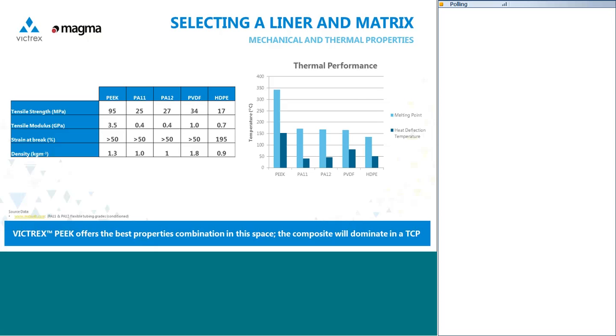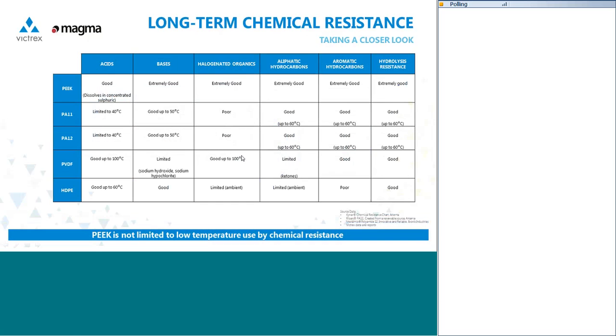So when you're selecting your liner and your matrix, your mechanical properties really relate to having a pipe which can be readily handled and can be used as a precursor for the full composite. The actual mechanical properties then almost fade to insignificance because of the composite which is put on the outside. What is important about the liner, the precursor, is that it has excellent chemical resistance. This is probably the most important function of the liner.